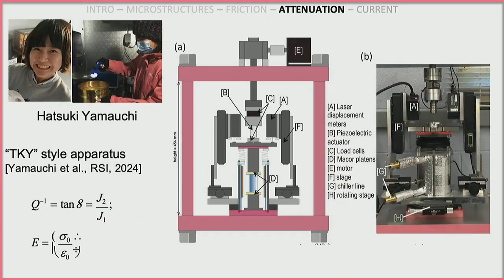In our lab here at Lamont, we've built a new apparatus that is based on the really nice high-resolution one we used in Japan. Postdoc Hatsuki Yamauchi came, and it's the apparatus that both she and I have used. She built this, adapting it for low-temperature work. A lot of nice elements to it: it uses lasers for displacements, so you can really get high resolution for your strain, and the stress is applied by a piezoelectric. You just get really nice quality data.